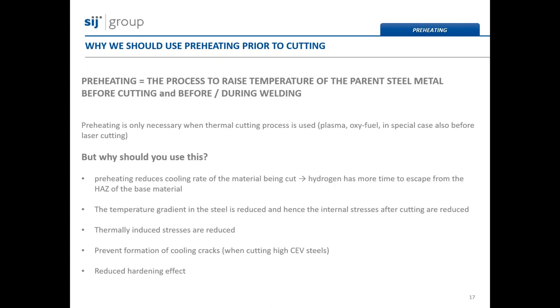We also have to point out some important factors why we should practice preheating. The first one: if the preheating is used properly, we reduce the cooling rate in the area near the cut edges. So hydrogen, as a result of the cutting process, has more time to escape from the material, resulting in minimized risk of crack appearance. Then the second one, internal stresses are reduced because the temperature gradient in the steel plate is also reduced. Then the third one, the thermal stresses during and after the process are reduced.